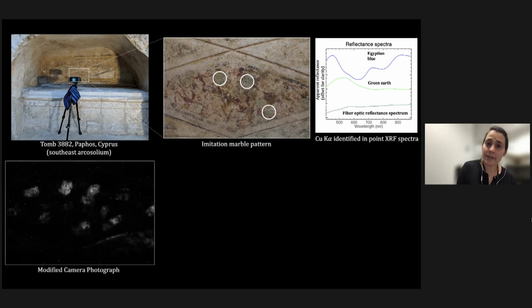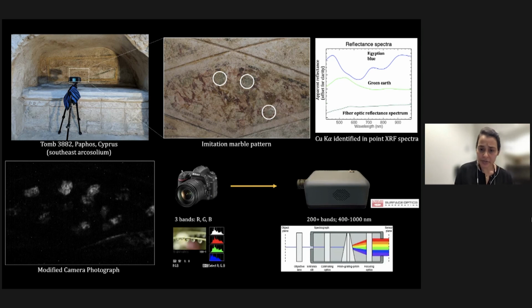So actually how I found out originally that there was Egyptian blue in there potentially was a modified camera. However, just using a modified camera doesn't give me any chemical information. And we know that we're just recording light from the scene, from the environment. So you cannot say that this light here has a peak at 900 nanometers. And so that's why I'm advocating that we transition to more robust imaging techniques to get us information that's both robust chemically, as well as giving us macro scale information.